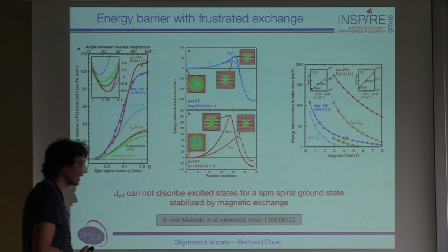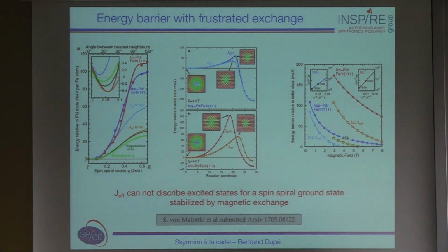Now, the question arises, what happens with the barriers? And that's what I show you here. Because if you think about it, when a skyrmion is collapsing, the angles between the spins are not small anymore. So you don't stay close here to this ground state, but you rather go here, you increase the angle between the spins, so you go higher in energy, and in these regions you have actually major differences between the full sets of DFT coefficients and J effective. So for HCP, palladium on iron on iridium 111, this is the barrier. You start with the skyrmion, you increase the energy as a function of the reaction coordinates, and then you fall into the ferromagnetic ground state. And so the barrier here is not so much different. You maybe have 20 meV difference, which is not that large.